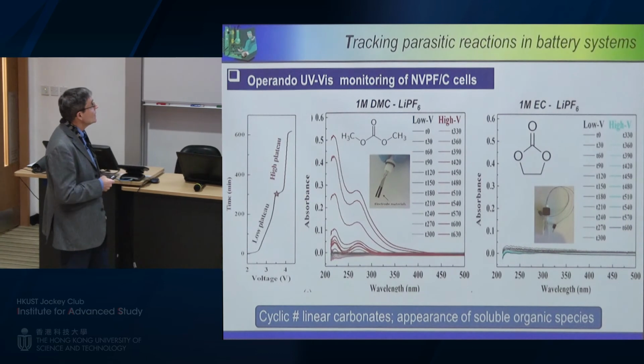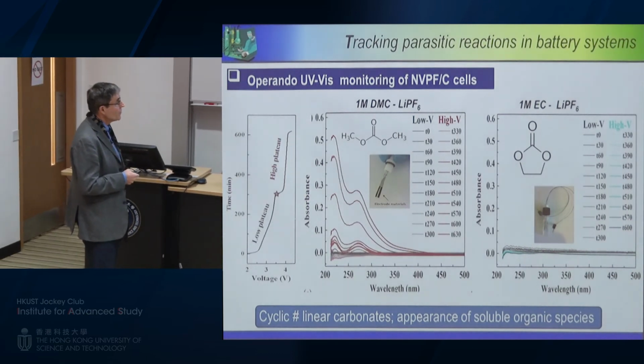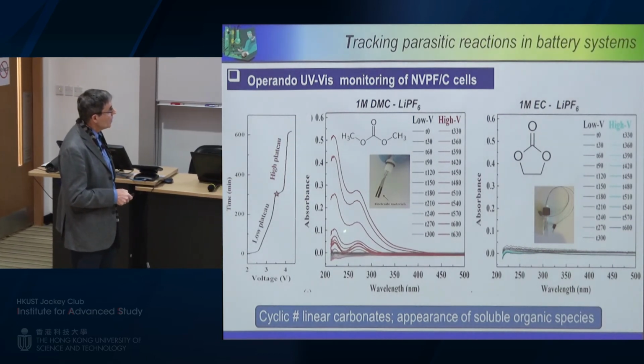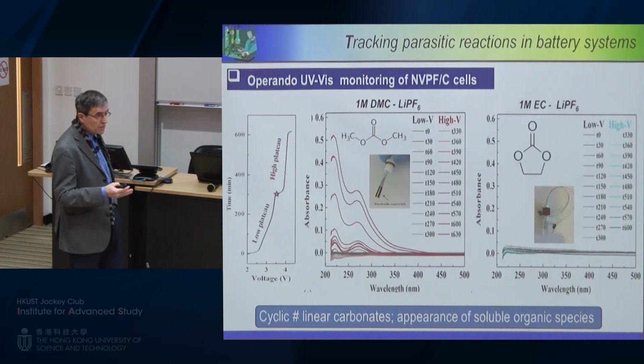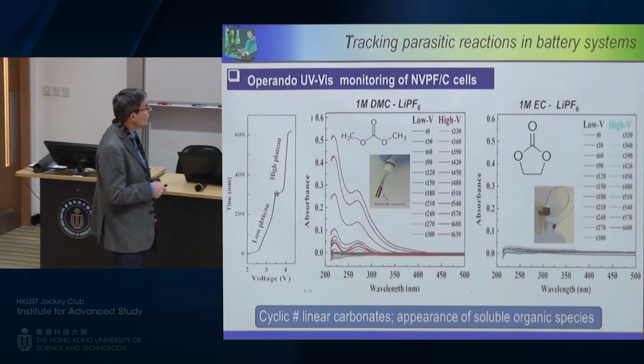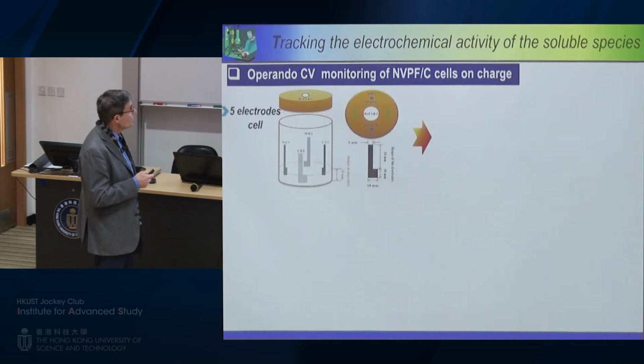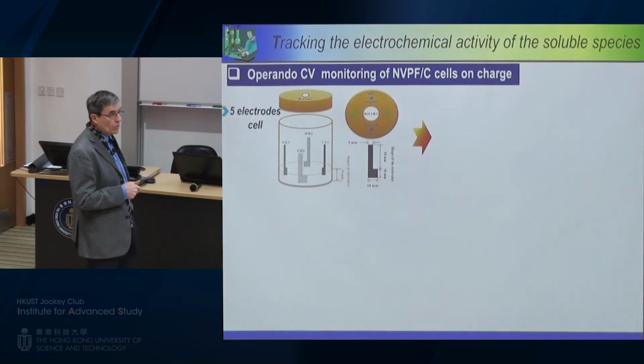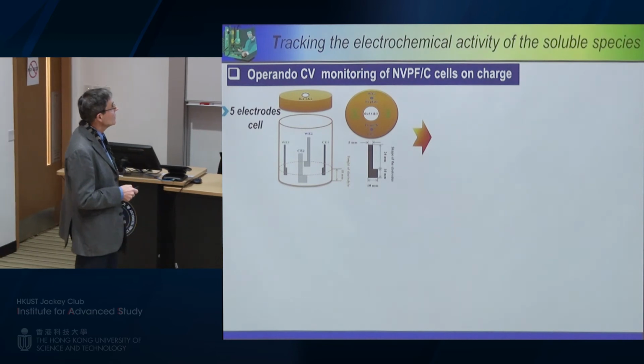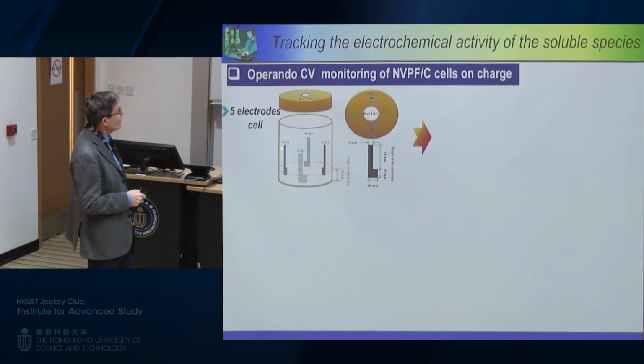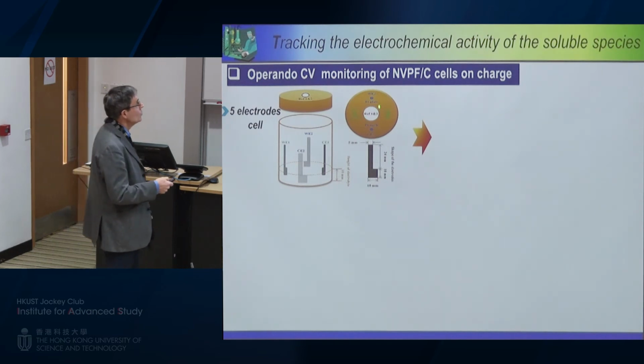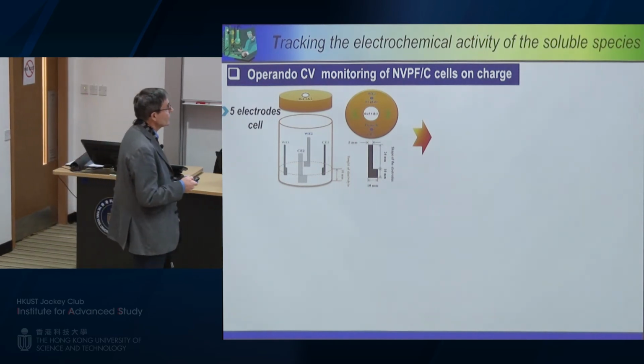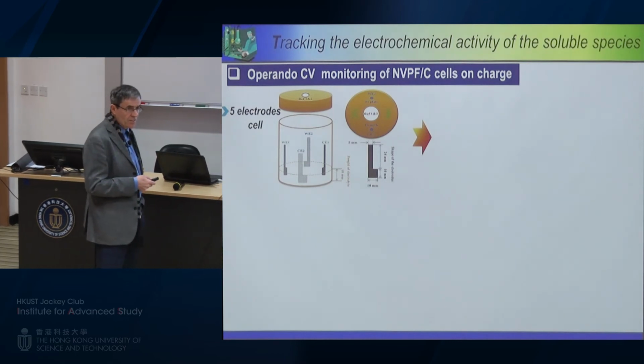So it looks like the problem was coming from this linear carbonate. So in this case, we decide to go one step further and try to see now what was the activity or electrochemical activity of this released species. To do this, we designed this kind of 5-electrode cells, where you are going to cycle the cell in a galvanostatic way between these two electrodes, WE1 and C1, and now you are going to collect cyclovoltammogram between these two platinum plates and platinum mesh. So we did this again for EC.